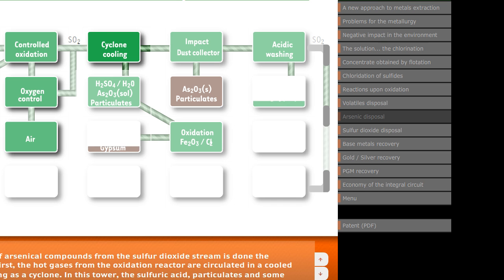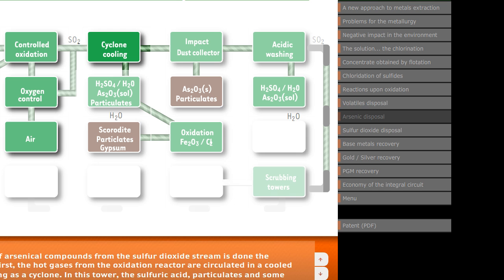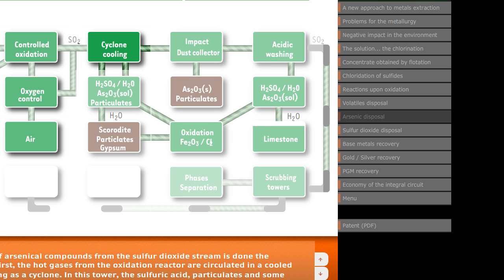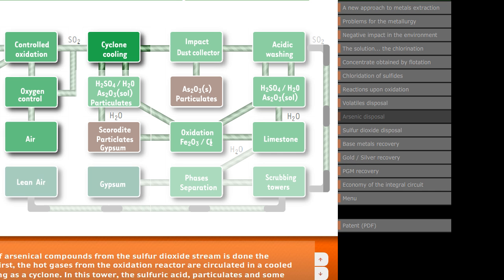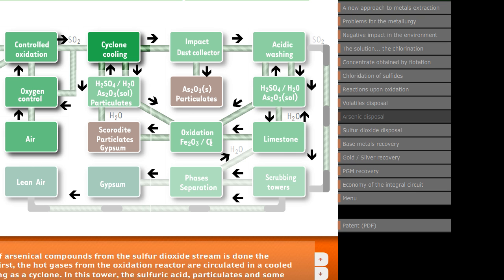After cycloning, the gas stream is circulated through an impact dust collector, and then through an acid washing tower, where the last traces of arsenic are removed. This acid washing is also oxidized and neutralized with limestone, in order to transform all the arsenic in the form of a neutral and stable solid made of scorodite and gypsum. This solid residue, along with the solid collected from the impact dust collector, can be disposed of safely in sealed containers. With that approach, arsenical compounds are concentrated in solid form and can be prevented from being recirculated in the environment.